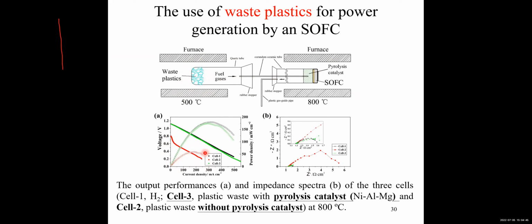Then we tried adding a pyrolysis catalyst on top of the anode catalyst, hoping to significantly reform the biogas. Using the catalyst on the surface of the SOFC anode, we can significantly improve fuel cell performance—the power density is increased very significantly.